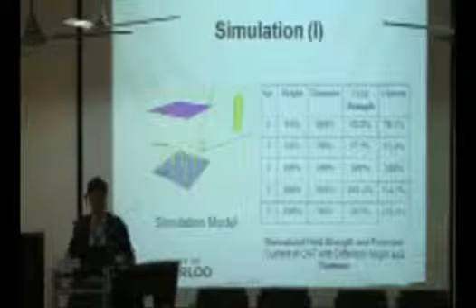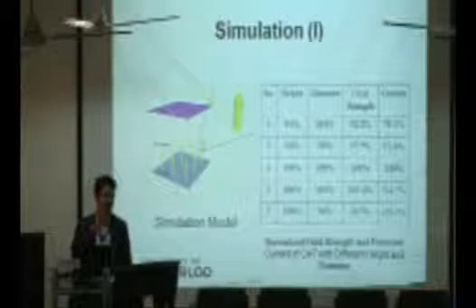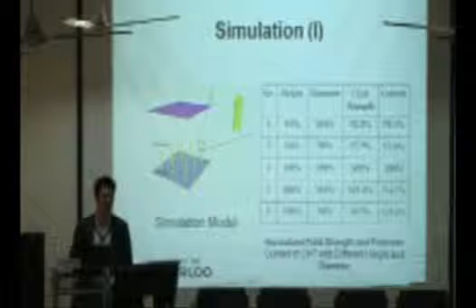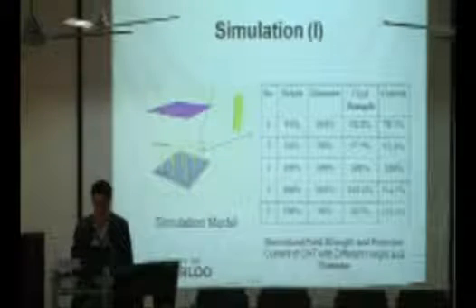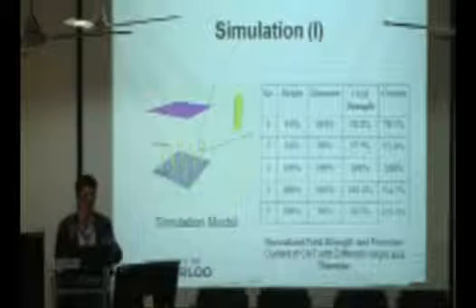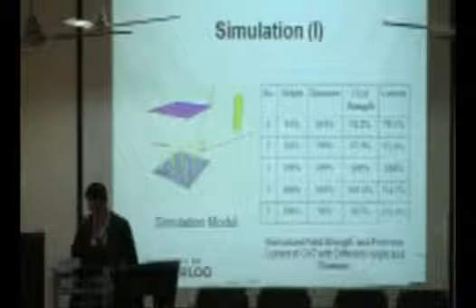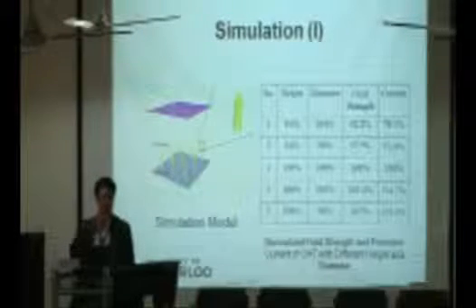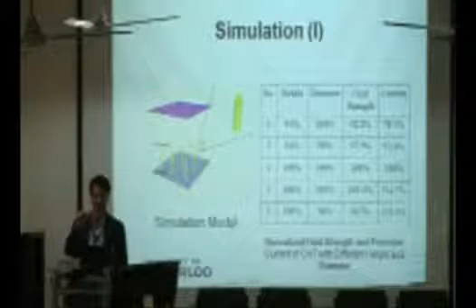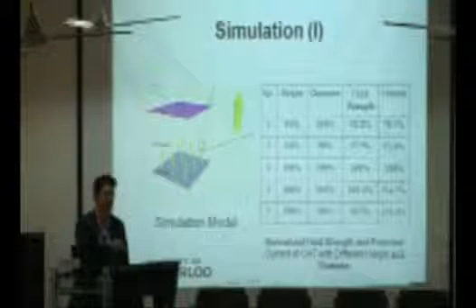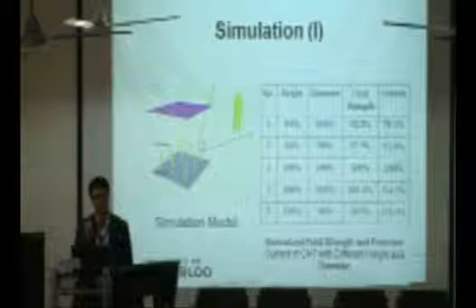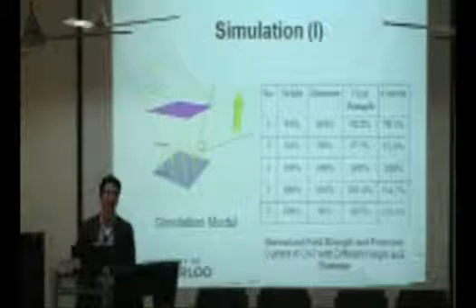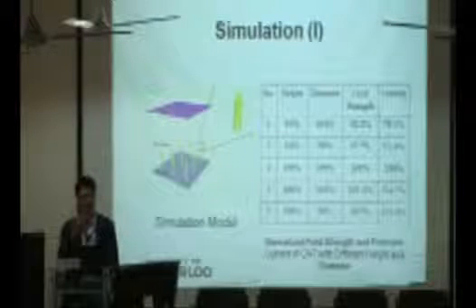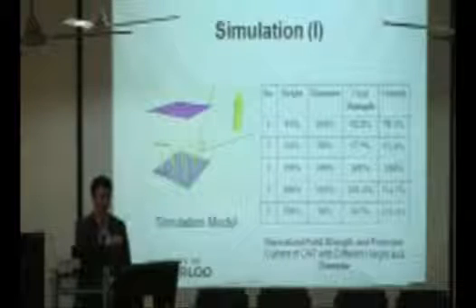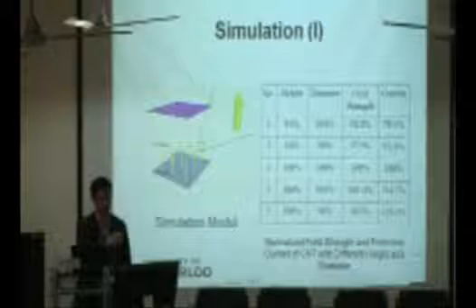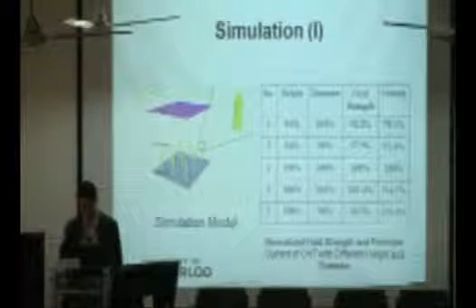Now, if one looks at the fabrication process of CNT, a 6% difference in height is actually pretty good. But even given a very good fabrication process, we still have to tackle the problem of huge non-uniformity in current extraction. This is particularly important for X-ray generation, because if the current is not stable, then the photon generation is not stable, and hence the image quality cannot be guaranteed. This is from the diagnostic perspective. From the therapeutic perspective, we want to guarantee the number of photons that we're using to irradiate a cancer patient. If the number of photons is fluctuating by more than 20%, then we have a huge problem.